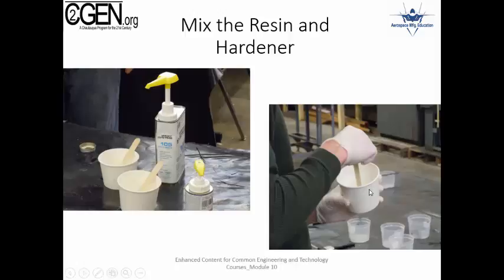Do this at 1 minute intervals for about 10-15 minutes, and you'll observe that the liquid flows slower and slower. That is, it's getting thicker, or the viscosity is rising. That means that the resin is actually cross-linking, and so it's starting to harden, or it's starting to cure. Doing this exercise will give you a feel for what the pot life or open time of this resin is.